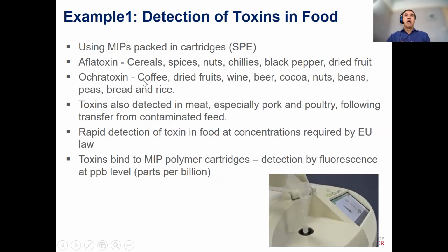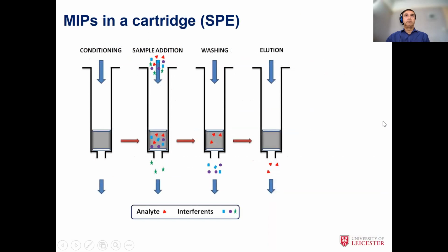But once they're above a particular limit that is regulated and controlled by the EU, then you can start falling ill. So what we've done is we've packed some MIPs in cartridges that we've made specifically for these types of toxins. And then you can put them inside a machine and you can actually detect the presence of these toxins that are fluorescent at parts per billion level. So that's a very interesting way of using MIPs for food sensing and food diagnostics.